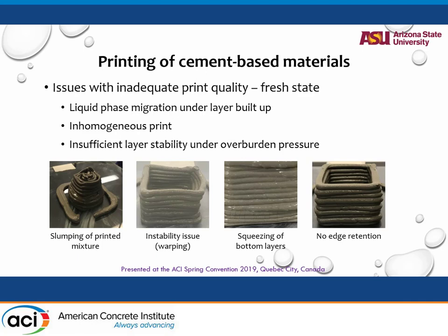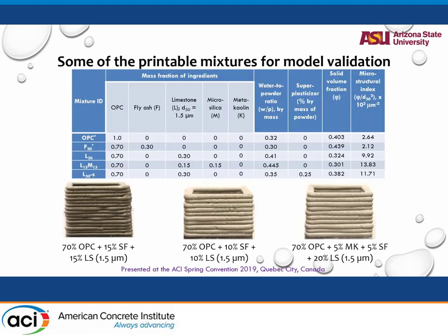Just to show some failed attempts with 3D printing — extreme compression and crushing of bottom layers, instability warping, edge retention not being good. The idea was to get some kind of printed mixes with a microstructural packing index on the order of 10³ µm². If you do the calculation of slip with respect to the volume fraction of particles in those mixes, you will see that as the number gets to about 10 or more, you have very good control over slip at the edge of the pipe. This is velocity-dependent — don't generalize this beyond the lab-scale printing velocities we used.